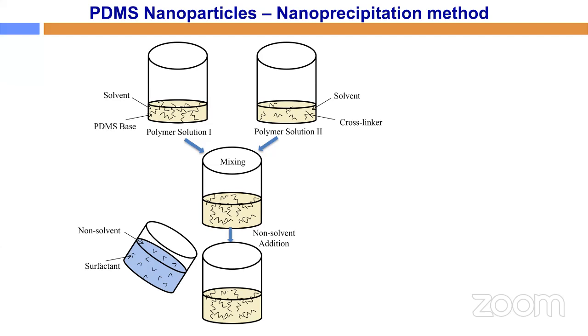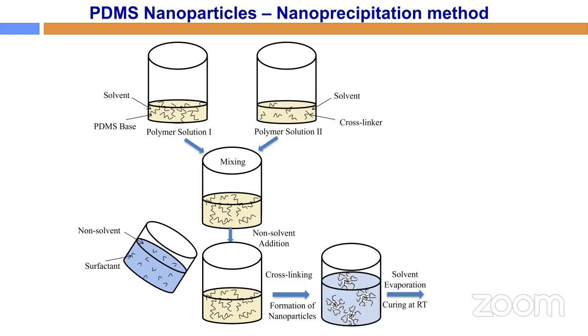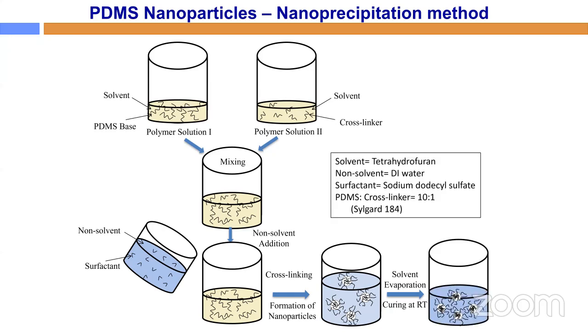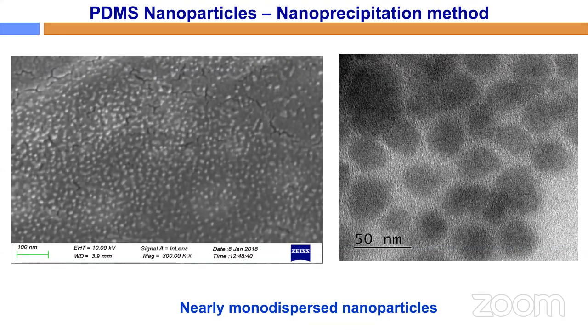Here the trick is done by the surfactant. Because of the surfactant present there, the PDMS forms as a nanoparticle decorated with the surfactant. So again, he has done all this treatment, and he got a very nice nanoparticle. In this case, the surfactant we used is sodium dodecyl sulfate. Now the nanoparticles are highly monodispersed. The size is less than 50 nanometers.